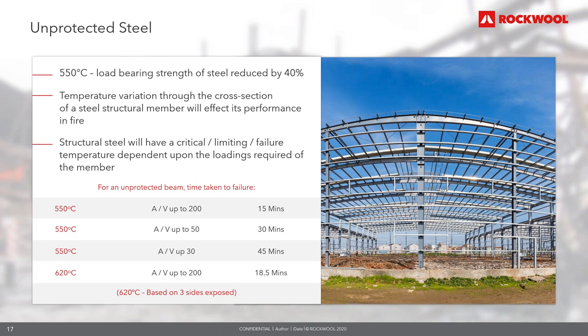Temperature variation through the cross-section of the steel structural member will affect its performance in fire, with the difference being as much as 200 degrees C between the upper and the lower flanges. So structural steel will have a critical or limiting failure temperature dependent on the loading required of that member. The higher the critical temperature, the less fire protection the structure requires, and vice versa.